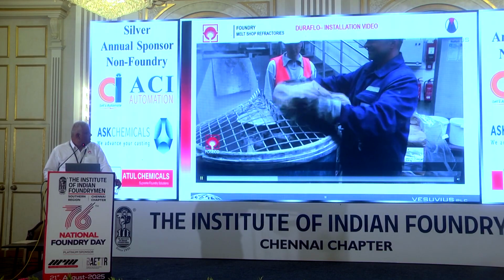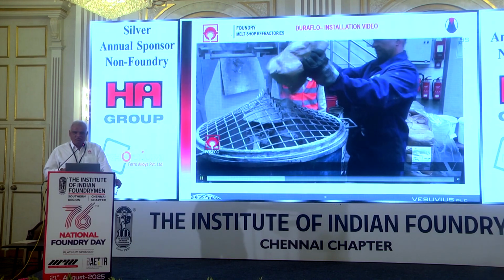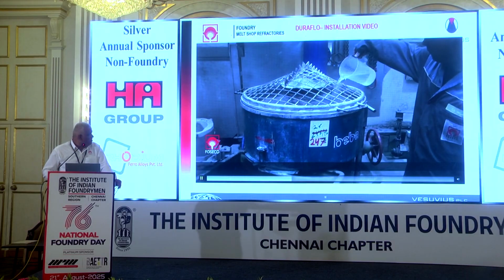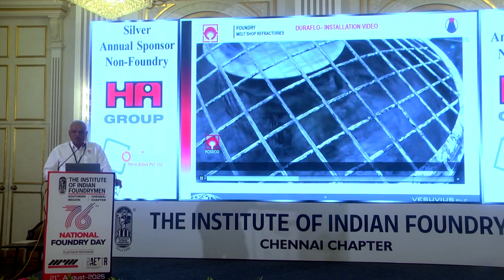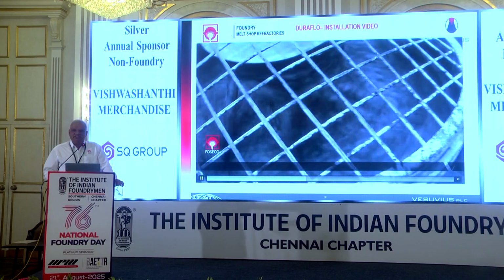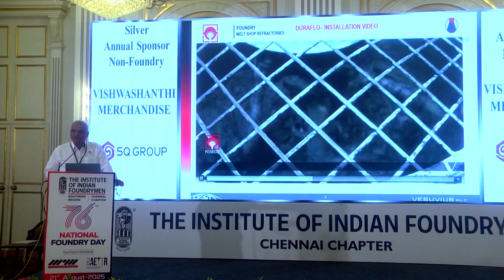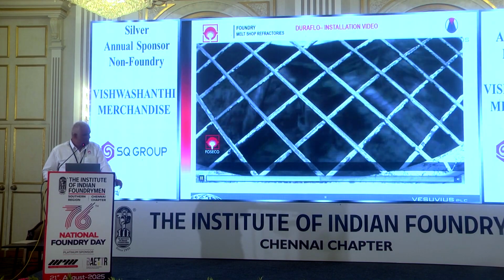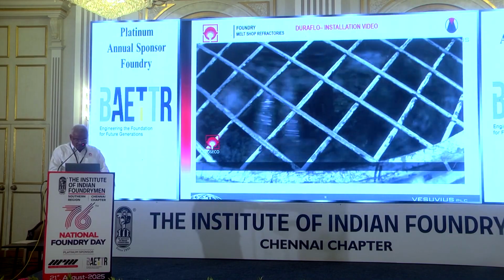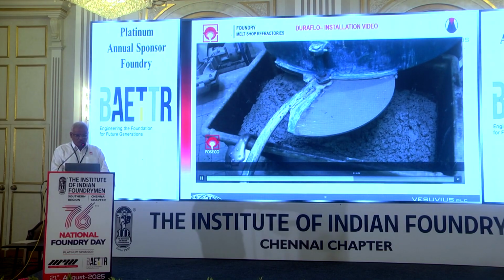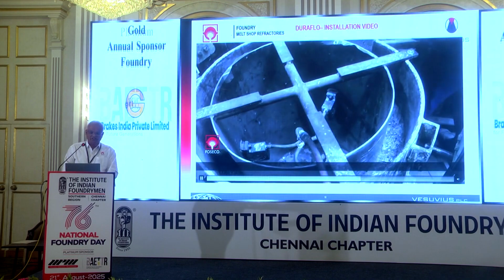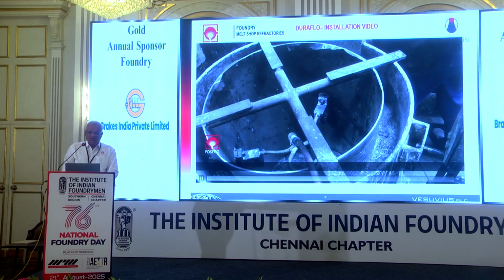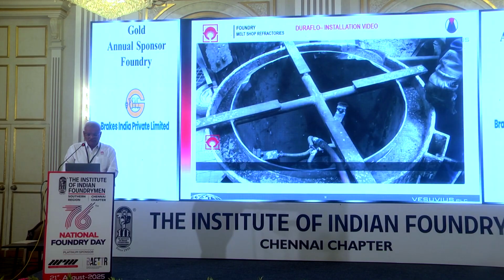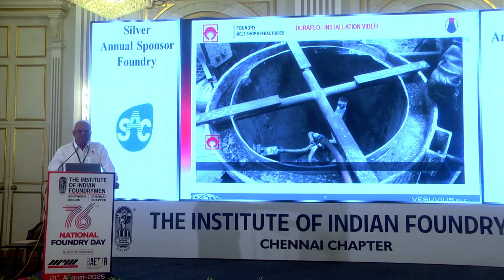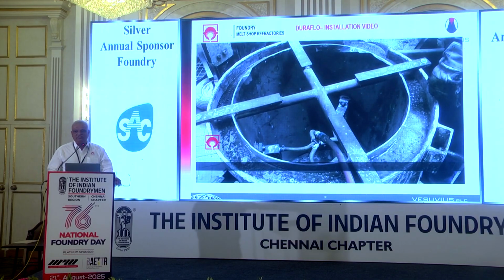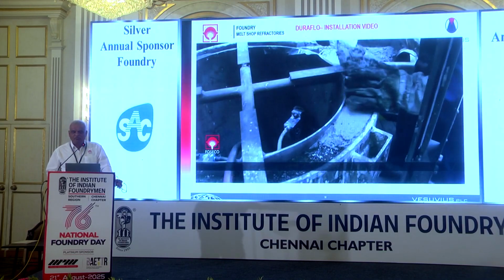In this, the material is mixed with water in the mixer, and then it is poured in the gap between your former and ladle. As this material has a self-flow tendency, there is no need for vibrators and all these things. This is the consistency after mixing in the mixer, so you can easily pour that material in the ladle cavity. Once it is covered, we have to let it settle for around 2 to 3 hours. Then we can remove the former and you can start preheating the ladle.